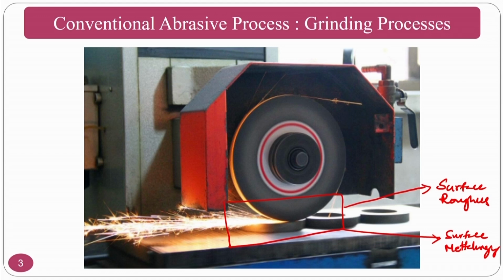Because of high temperature, it will sometimes burn the surface. At the same time, it will degrade the surface. Suppose the parent material grain structure is of size X; you may get a larger or smaller size, because the size of the grains will alter due to the temperature generated during the process. That is why we use cutting fluids in the grinding process. If you do not use them, there are a lot of problems. If you do use them, there are some other problems, which you have seen in previous classes.